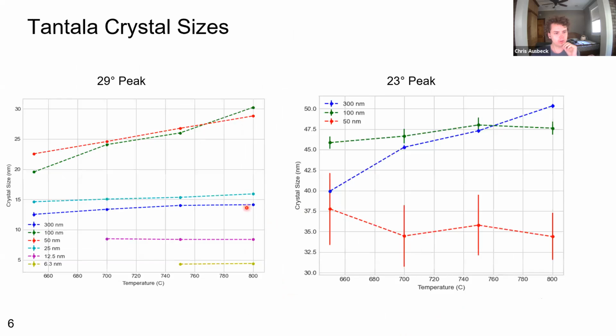So here are our graphs for our crystal sizes for the 29-degree peak and the 23-degree peak. So for the 29-degree peak for 300 nanometers, this one is actually only around 14 nanometers large. But for 100 nanometers and 50 nanometers, these go up to around 30 nanometers. 25 goes up to around 16, 12.5 to 8, 6.3 to 4. For the 23-degree peak for 300 nanometers, the crystal sizes go up to around 50 nanometers, 100 goes to around 47, 50 goes to around 35.